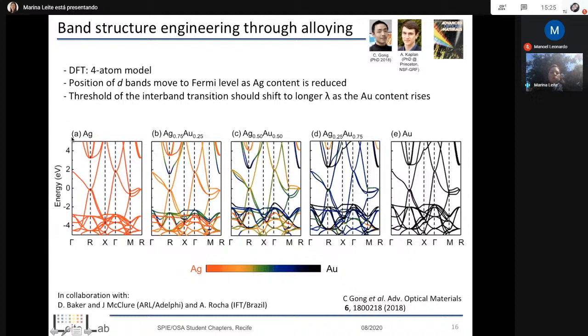So here what you're seeing is the band structure of silver, very textbook. If you use Kittel or Ashcroft in your classes, that's exactly the same thing here. What you're seeing is the band structure for FCC silver, same thing for gold here in black. But it was really cool in the calculations that Alexandre did, that we could now resolve the contribution of each one of the elements. So what you're seeing here is that, for instance, once we add a little bit of gold, only 25% gold, it completely dominates the band structure, right?